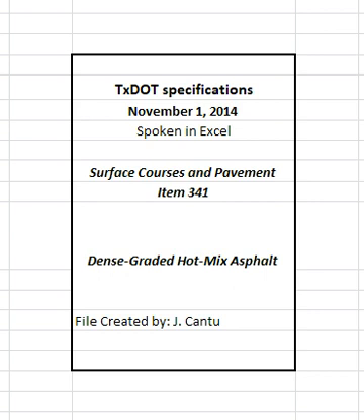The engineer will use the department's mix design template, when electing to verify conformance, to calculate the percent of Class A aggregate retained on the number 4 sieve by inputting the bin percentages shown from readouts in the control room at the time of production and stockpile gradations measured at the time of production. The engineer may determine the gradations based on either washed or dry sieve analysis from samples obtained from individual aggregate cold feed bins or aggregate stockpiles.